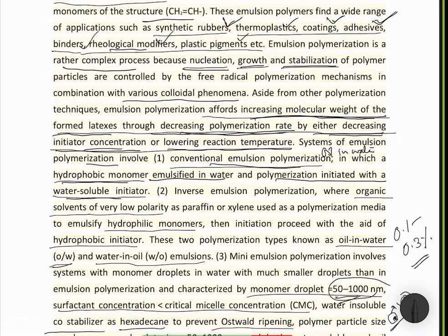Then we can have the inverse emulsion polymerization system, meaning just the reverse, where organic solvents of low polarity such as paraffin or xylene are used as the polymerization media, and hydrophilic monomers are emulsified within it. So here you have just an inversion of the role of the components, that is your hydrophilic monomers are emulsified within a non-hydrophilic dispersion medium, and the initiation proceeds with the aid of hydrophobic initiator.